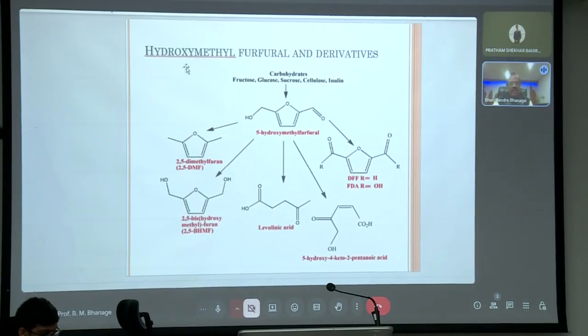As I told you, we can get hydroxymethylfurfural, which can be converted into various derivatives. For example, one side you have hydroxyl group, another side you have ketonic group, aldehyde group, and this can be converted to either dicarboxylic acid, which is a kind of monomer for biopolymer, or you can convert that via hydrogenation to 2,5-dimethylfuran or 2,5-DMF. Again, this is a very useful solvent. Or you can do the hydrogenation at the aldehydic part and you can get bis-hydroxymethyl group, that is called 2,5-BHMF, and this is also some kind of useful monomer for biopolymer.